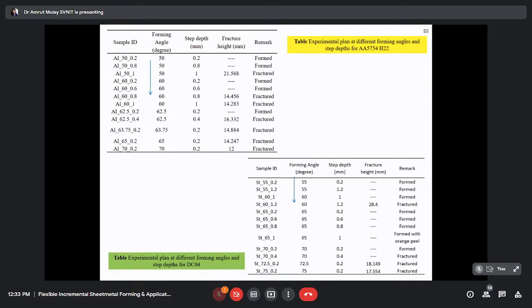So here in the CNC machine, we control the step depth only. Only we change the step depth. The step depth is changed from 0.2 mm, 0.8 mm, 1. Now you can see the forming angle is also changed. So based upon our geometry, the program will change. The particular program is made for step depth and forming angle, and the remaining parameters are kept constant for all the tests. So feed rate and different parameters are kept constant.